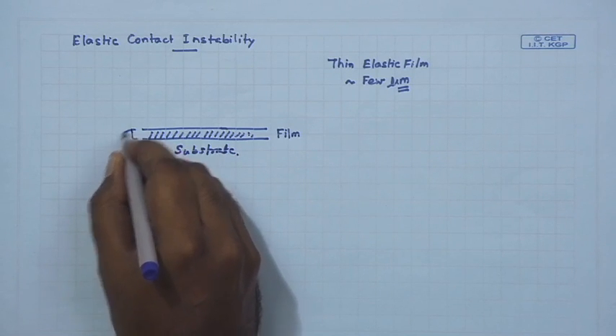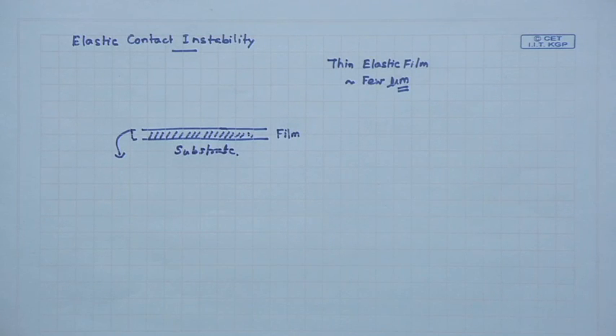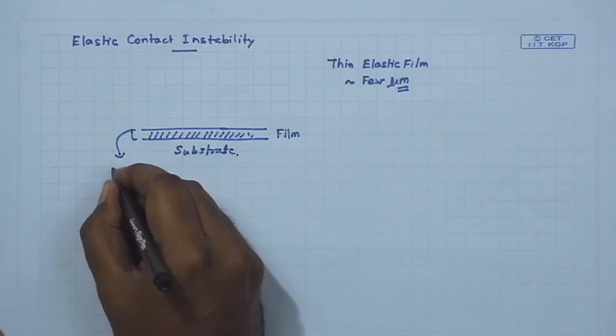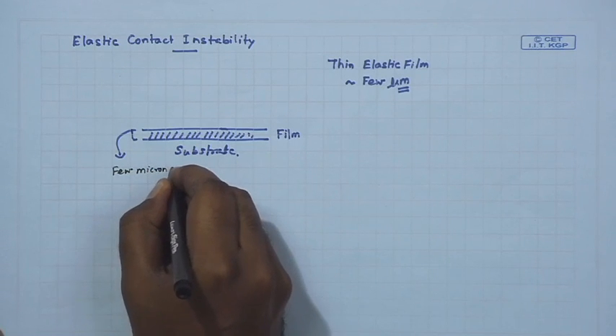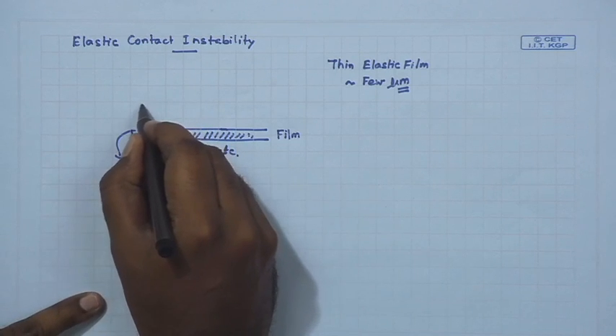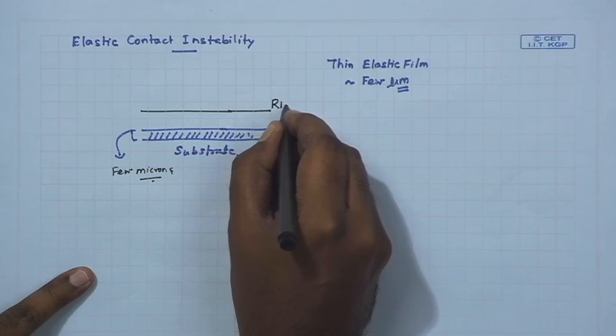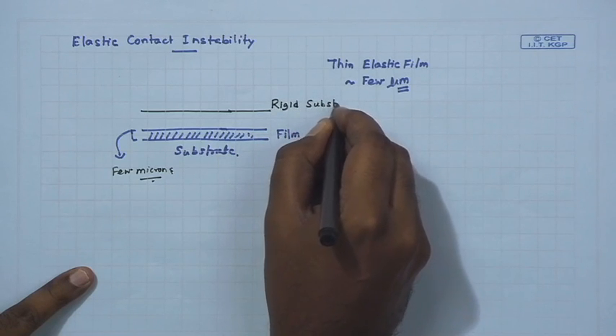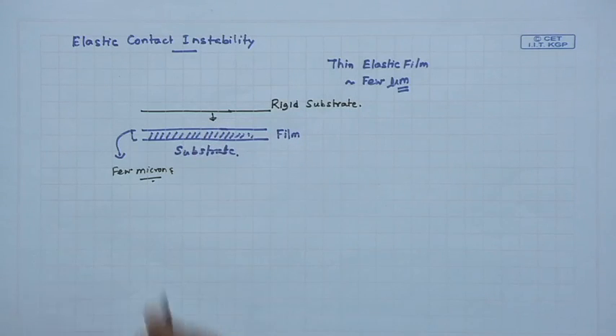This film now, if you compare with what you have already learned in case of dewetting, has zero disjoining pressure, or the effective interface potential within the film is zero, simply because the film is too thick. As I mentioned, the film thickness is of the order of a few microns, and therefore that is not the concern. But the issue is that you have another rigid substrate which is progressively coming in contact with the film. I will take help from the AFM literature to use the word approach. That's the easiest way to describe the situation, isn't it? A rigid surface is approaching a soft elastic film coated on another surface.